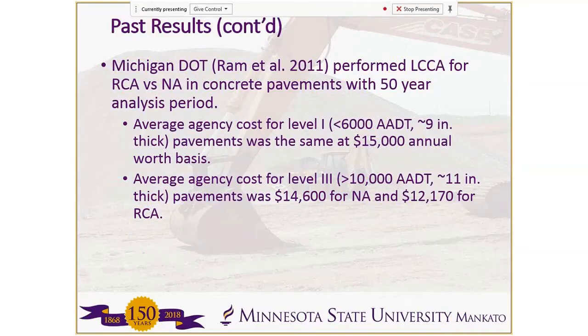Michigan DOT also performed a study, a lifecycle cost analysis for RCA versus natural aggregates. If you remember, Michigan was one of those states that had the highest number of trial projects with RCA. So they found that for level 1 pavements, which they define as less than 6,000 AADT and approximately 9-inch thick, the cost was the same between the two types. The cost was about $15,000 on an annual worth basis. For level 3, the cost was actually less. So the economic cost was actually less for the RCA, $12,170 for the RCA versus $14,600 for the natural aggregate. So their analysis is showing a better economic value using the RCA concrete.